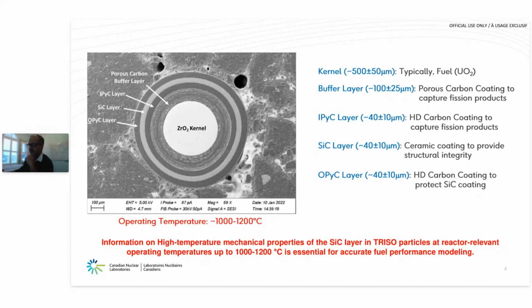The operating temperature for these fuels is about 1,000 to 1,200 degrees C when they will be used in reactors. So we need information on the high temperature mechanical properties of these different layers around the fuel kernel. In particular, I'm going to talk today about silicon carbide layer at reactor relevant operating temperature to accurately model the fuel performance itself.